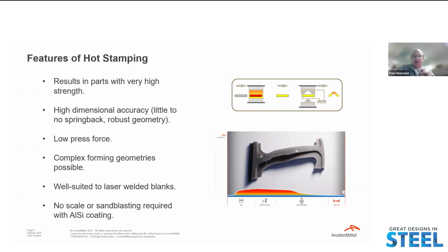Dimensional accuracy, particularly for the strength of the parts, is achieved as springback is all but eliminated. Press force is lowered in the direct hot stamping process as the actual forming action occurs in the heated, lower strength blank. The hot stamping process is well suited to the use of laser welded blanks, providing an opportunity to mix PHS grades and thicknesses to optimize and tune performance as needed in a particular area of the vehicle architecture.